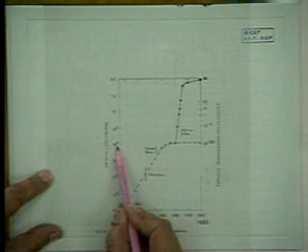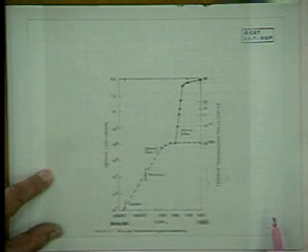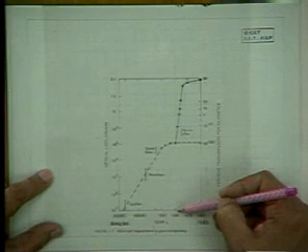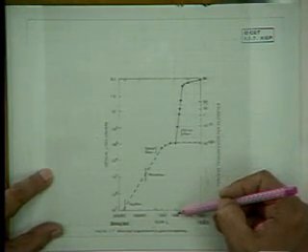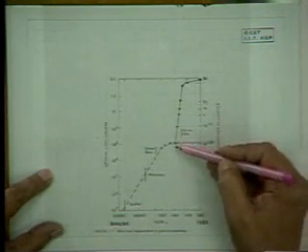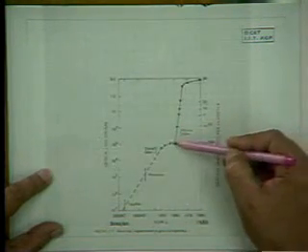Until about 1966, the optical loss was of the order of 10 to the power 3, that's 1000 dB per kilometer. It was about this time that Kao and Hockham predicted that glass could be an ideal material for transmitting optical signals, and thereafter the loss in optical fibers reduced dramatically from 10 to the power 3 dB per kilometer to 0.2 dB per kilometer.